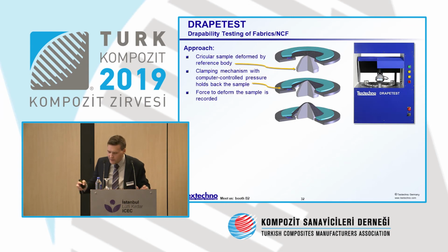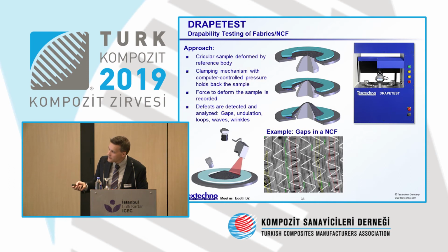What we do here is we hold a sample of about pizza-sized shape, 30 centimeters across, with a ring. And then from underneath, there's a piston moving in, forming it into different drape heights, forming it into a different shape. And while we're doing this deformation of the fabric, we can actually monitor what's going on with 3 different monitoring systems. There's 2 cameras and a laser triangulation. And in this way, at each height of the draping process, we can tell you how many gaps there are, how many undulations are happening, and if there's any waves.